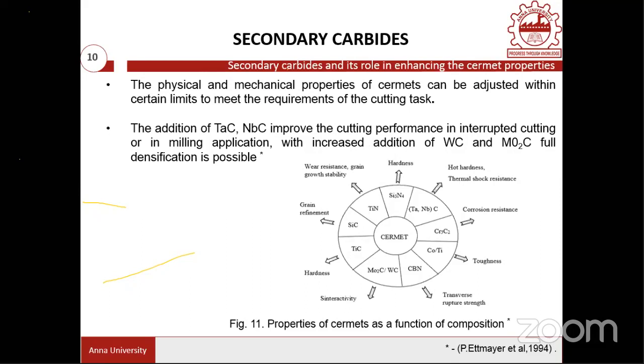Then Si3N4 can be added to improve the hardness value. And the hardness can also be improved by tantalum carbide and niobium carbide. And specifically, if the tool has to be corrosion resistant, then Cr3C2 can be added. And for improving the toughness, you can add cobalt, nickel, titanium, any metallic element which acts as a binder material. Then the toughness can be improved. Then you have cubic boron nitride, which can be added to improve the transverse rupture strength.